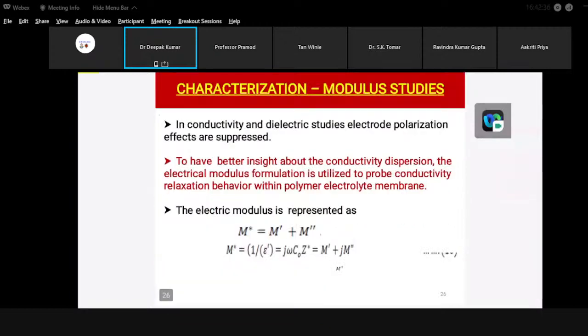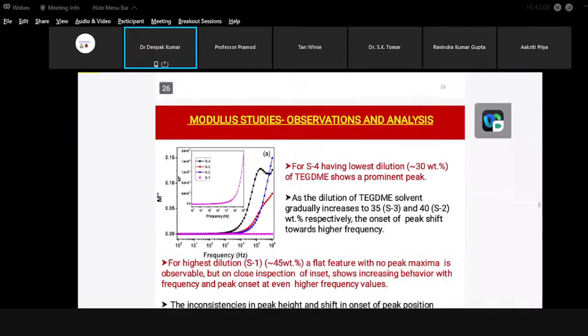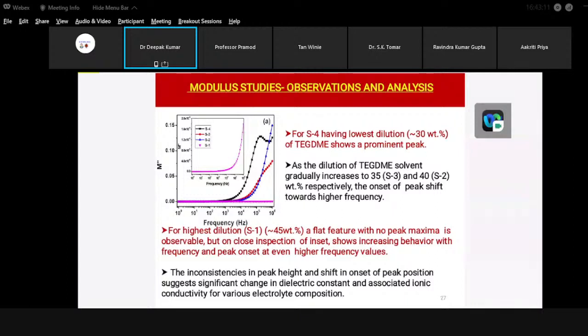Now, to further investigate the ion dynamics, we have performed the modulus investigation also. The modulus is represented by M prime and M double prime. In the case of the dielectric behavior, we are able to observe the features at the low frequency side. However, at the higher frequency side, we are not able to observe the features. So that's why the modulus formulation, which acts as a complementary kind of study, is utilized, and we can see some features at the high frequency side.